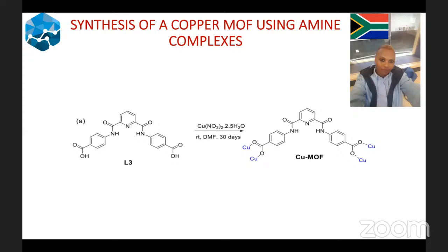Okay. So what I'm saying is, instead of increasing temperature to activate the MOF, probably we can run the reactions at mild temperatures by just modulating the coordination strength of the linker to the metals by adding a small amount of protons. That should just be an idea. I think that's interesting, and it can be explored to see if we can achieve the same results as with the activation.